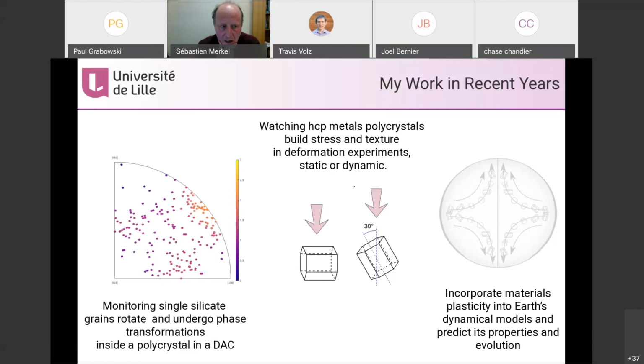This is something I've been wrestling with myself, because in some experiments I have a lot of grains and my positions are less constrained. But if I start with a single crystal, they're usually very well constrained, even if I don't use a half scan. My guess was more experimental, the wobble of the diamond cell. As you step scan, especially in this experiment on NaCoF3, we were doing resistive heating, so there are a lot of cables going to the cell, and sometimes the rotation is probably not as good as we think. So I suspect it's more the wobbling. When we do the laser heating experiment, it seems to be much better.